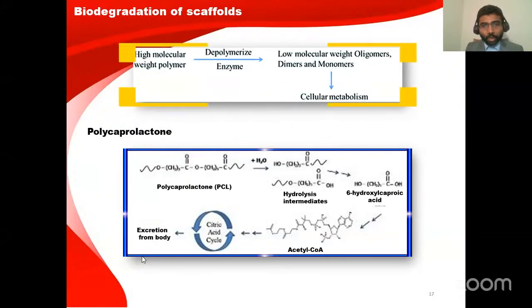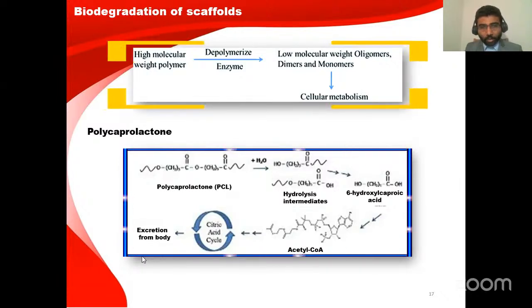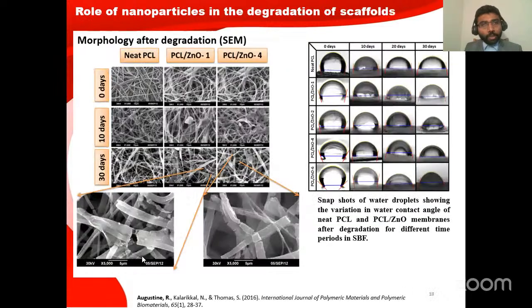Also, we try to improve the biodegradation of the scaffold. For example, polycaprolactone is a polymer that is biodegradable by hydrolysis. Such a hydrolysis process finally generates acetyl coenzyme A, which is used in the citric acid cycle. And we incorporated nanoparticles like zinc oxide to improve the degradation because of the specific properties that generate reactive oxygen species within the system. The zinc oxide nanoparticles' photo-oxidation capacity can also improve the degradation. When we incorporated around 4% zinc oxide nanoparticle, we got very high degradation of polymeric fibers, which is very important because optimizing the degradation of materials is very important.